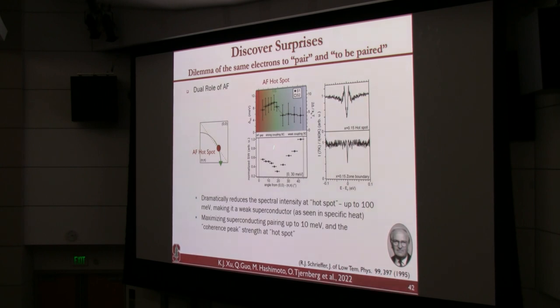Now, if you analyze more quantitatively, you can see that's the size of the superconducting gap at its maximum, and here is the density of states corresponding to a minimum. Also, when you're at the hotspot, you see a coherent peak of the superconductivity. But if you're far away, it's hard to see the coherent peak.